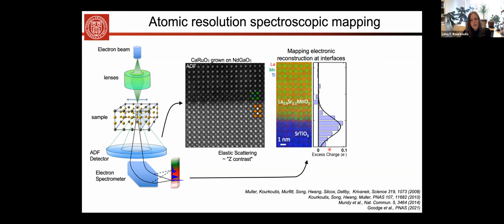And what we have been able to do is not only map the distribution of elements in that sample, but we have also been able to map the distribution of charge right at this interface. So here you see that we have about 0.1 electrons at its peak accumulating at that interface. And those kinds of electronic reconstructions are important to stabilize an electronic phase at an interface between two materials.